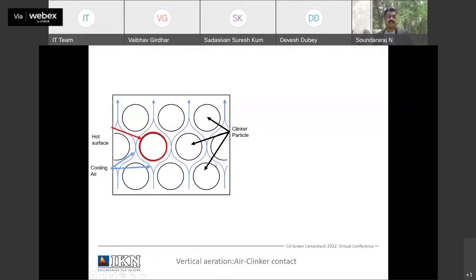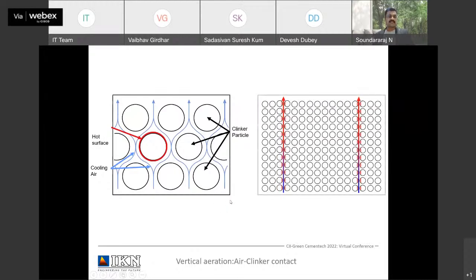In a real picture, if you assume 1 square feet of grate surface, how many clinker particles will be there? Maybe 10,000? In the vertical aerations there are limited holes and slots in a grate plate. Thus, in vertical aeration, there is a big gap between air to clinker contact. Anyone can understand from the picture that the effective cooling is not taking place in the cooler with vertical aeration.